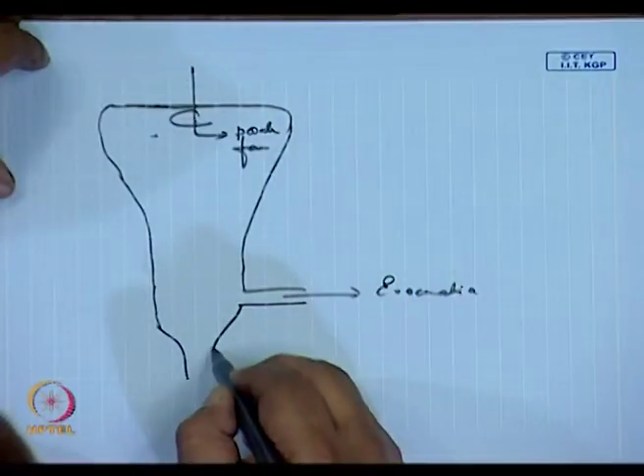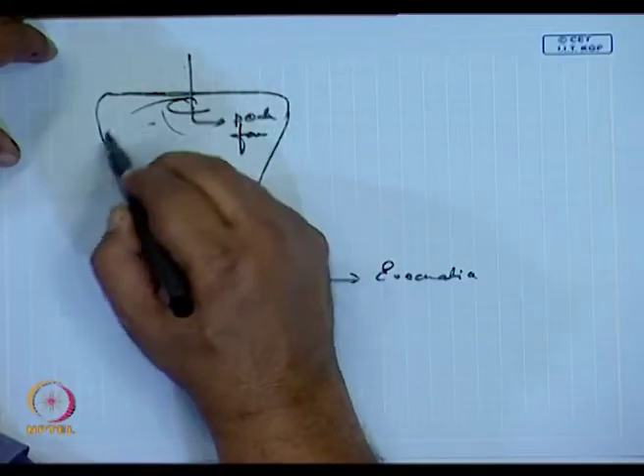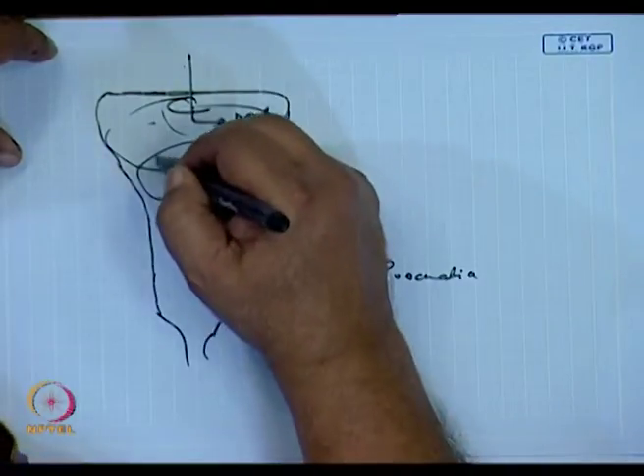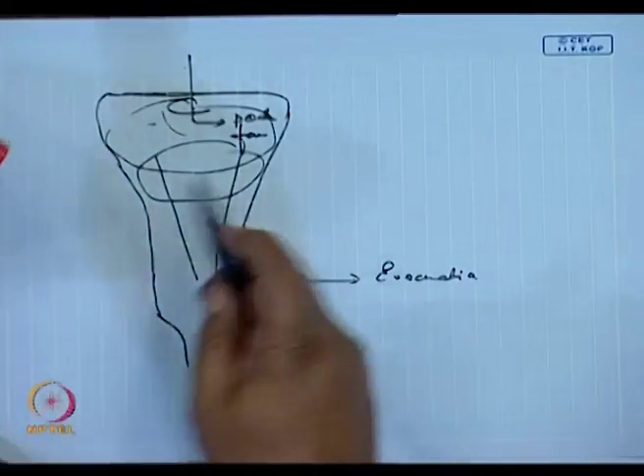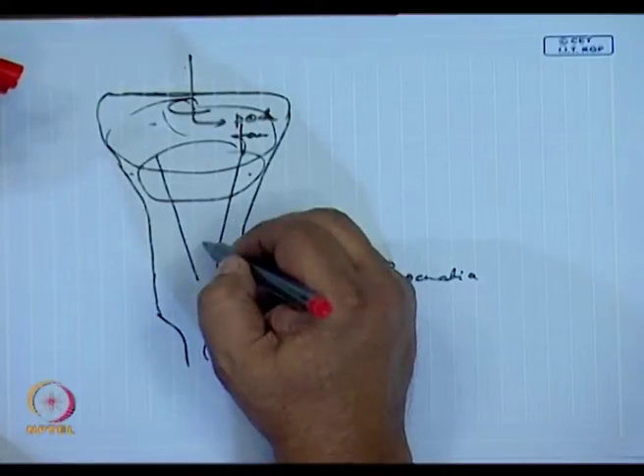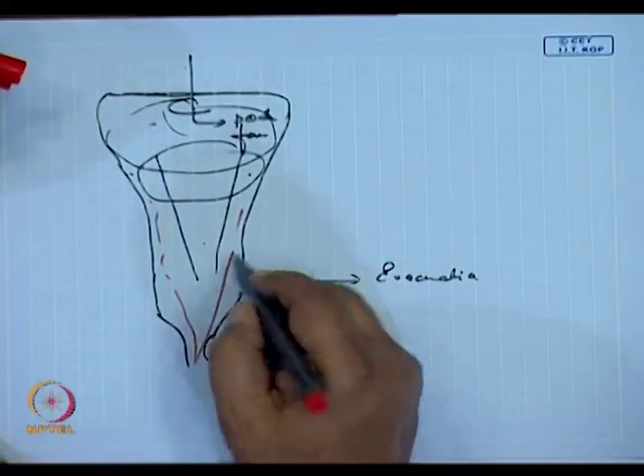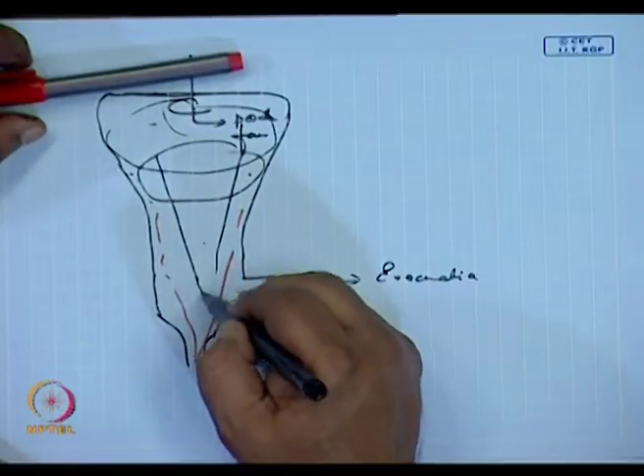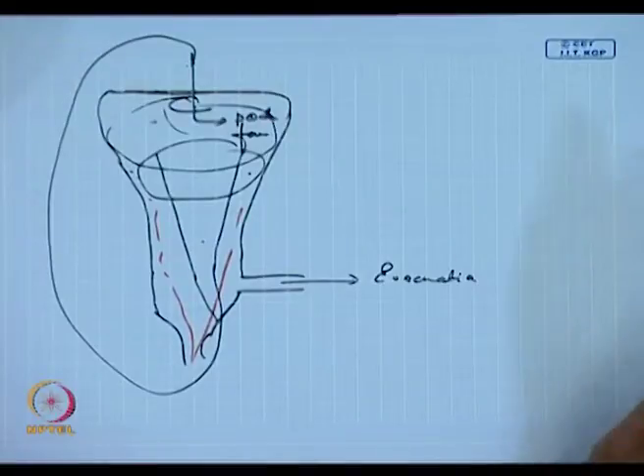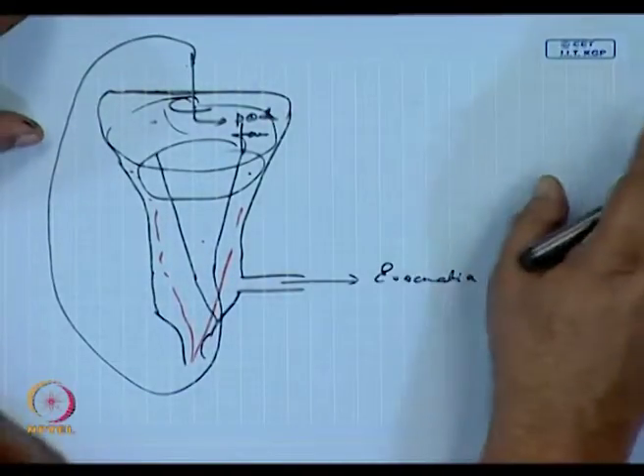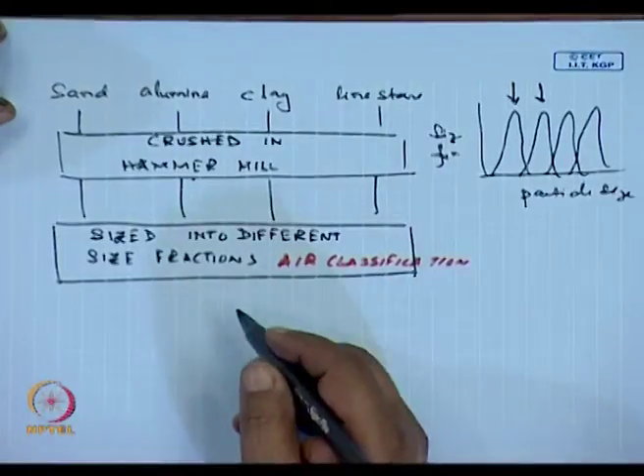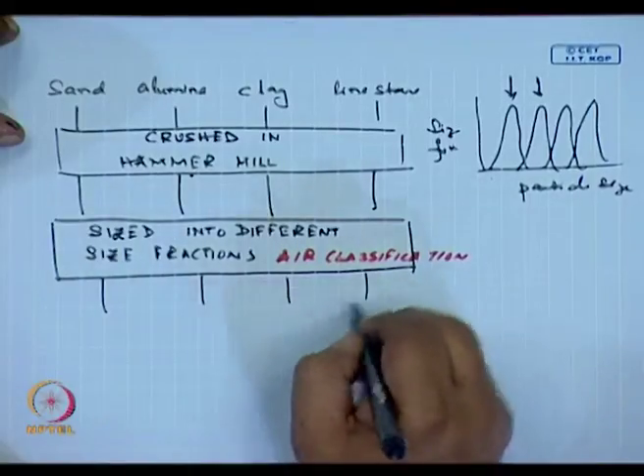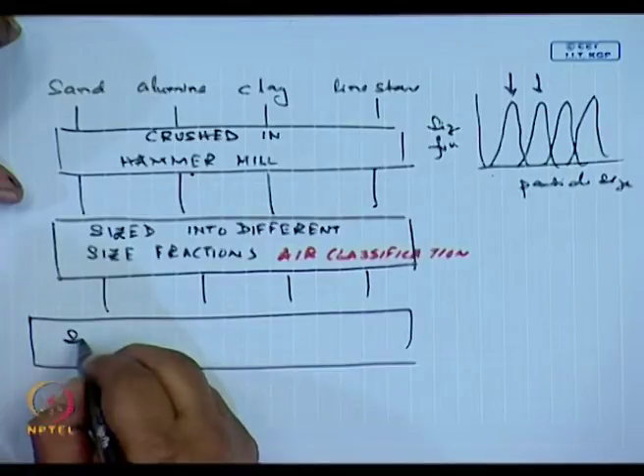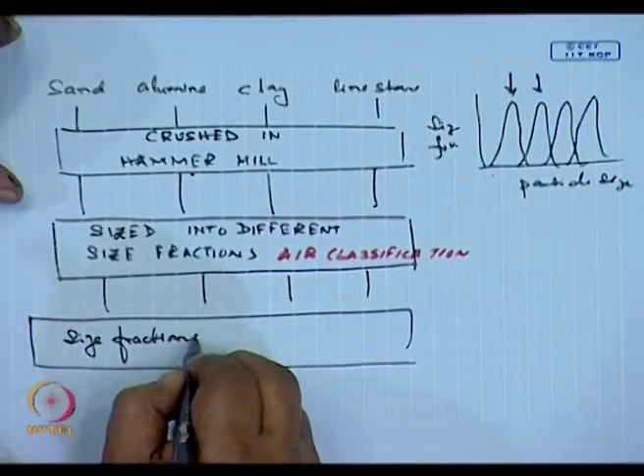I have shown this in detail earlier. The powder is fed in and there is a high velocity air in circulation. The finer powders circulate in the outer periphery, the coarser powder in the inner periphery. These finer powders are taken out. The coarser powders can be returned back to over here for grinding. There are various types of air classification systems available, and hence one can look them up on the net. So basically they are air classified, then size fractions are selected.